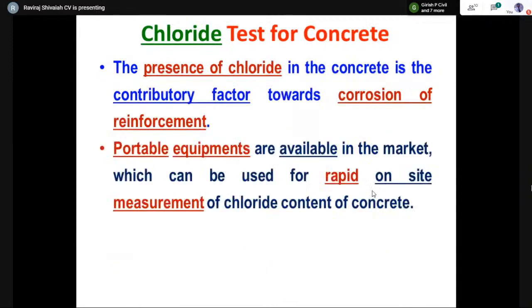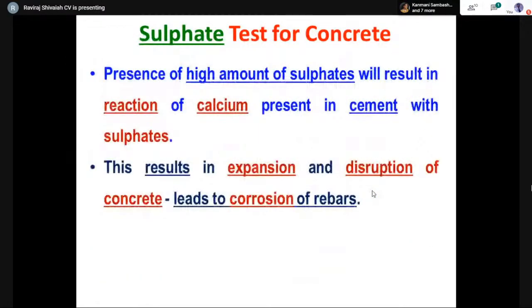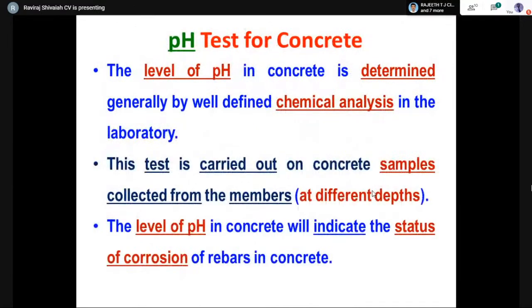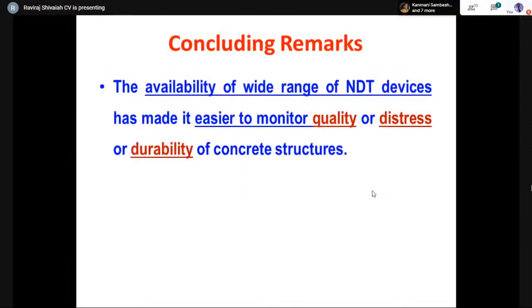So regarding the chlorides or sulfates or the pH, whatever we are trying to test, please understand, these again can be done using some simple chemical analysis, where we take concrete samples at different depths, like 5 mm depth, 10 mm depth, or 15 mm depth, take them to the laboratory, grind them to a very fine powdery form, and then do these kinds of analysis to determine the percentage of sulfate content, or the pH value, or chloride contents. We can then understand whether the values are within the permissible limit or not. If it is within the permissible limit, things are fine. Otherwise, we have to remove that concrete and make good with fresh concrete. We have to have a good cover concrete.